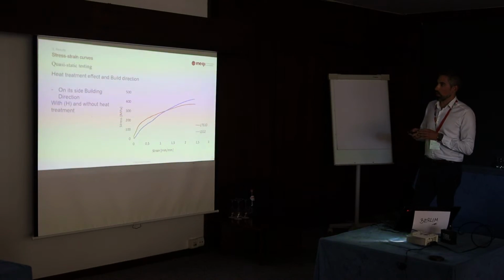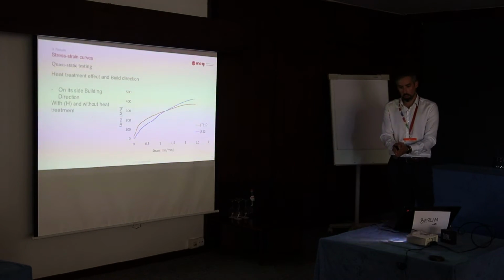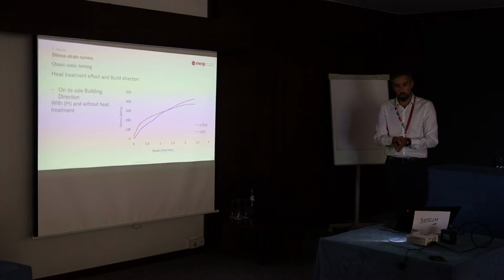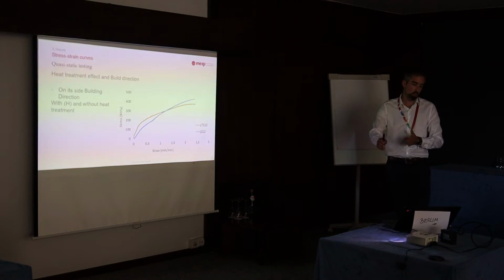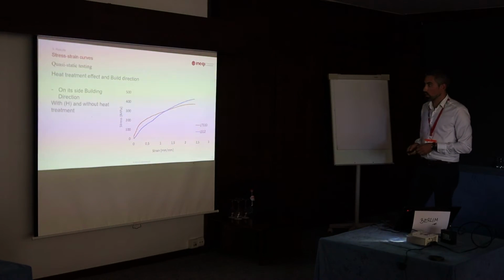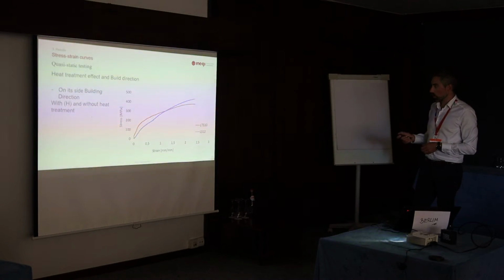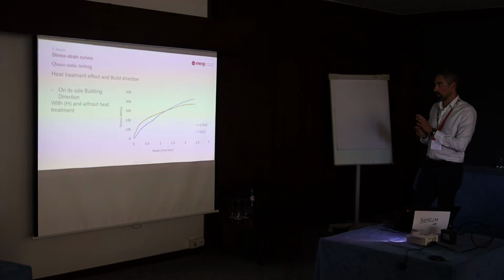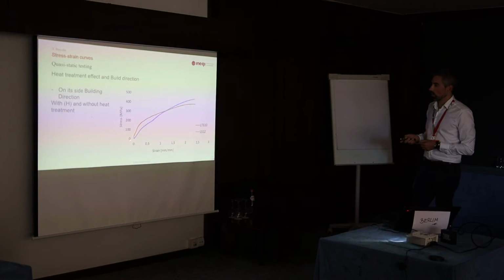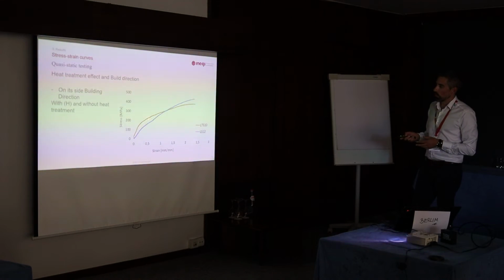This would be the one on the side, meaning the specimen would be produced on its side, so that the lines of deposition would be along the direction of the tests. We can see here that the effect is not as clear as in the previous section. You can see that for the quasi-static testing, even the heat-treated specimen varied in the beginning, and not only the expected behavior from material science.